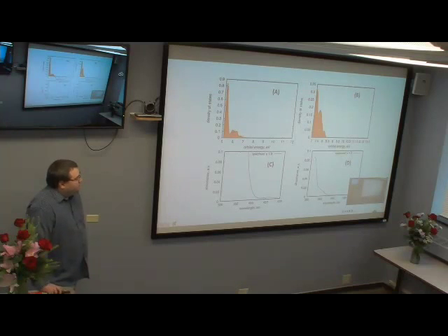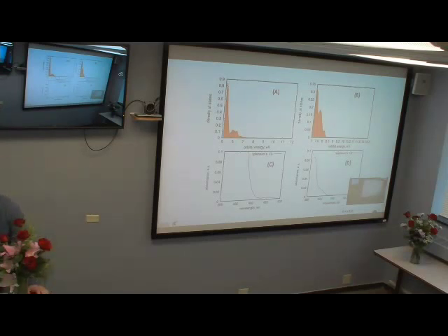I know that in these materials, when you use the larger halides, the band gap decreases, but that doesn't make sense for this situation. Iodine instead of chlorine, or bromine instead of chlorine, for instance, decreases the band gap, but that wouldn't make sense here. I am not sure what would cause that.